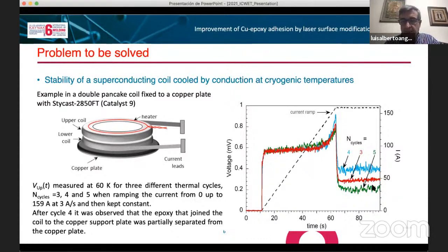So it means that in this coil, the tricky point was not the degradation of the coil due to the thermal contraction when you cool down or heat again, but the problem was that the coil was separate from the plate, so the cooling was not effective. And that's why every time you cool down, the temperature was a little higher, and then the voltage generated by the coil was increased. So these joints were not reliable, and we decided to study a little more if we could improve these joints.